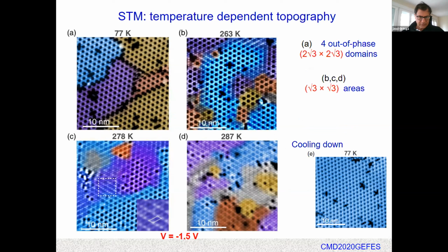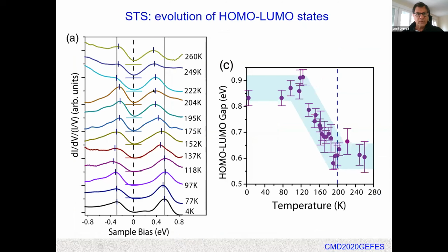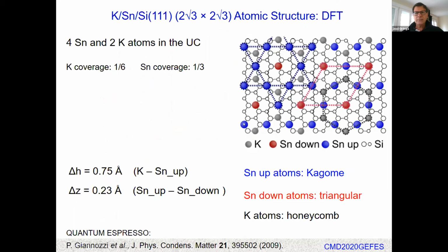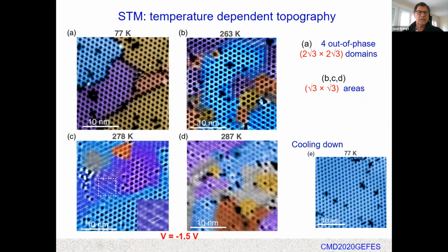STM topography for the voltage of −1.5 V, so occupied states. At 77 Kelvin, at low temperature, we see this structure, which corresponds to the 4 out of phase 2√3×2√3 domains that we have in this surface, indicated by the different colors. So I have to say what these 4 out of phase domains are. I'll go back to the structure. In the 2√3×2√3 unit cell, there are 4 atoms, for example, these 4 atoms. And depending on which one of them is the down atom, we have a different ground state, so we have a different domain. So these are the 4 different domains that we have here, which are out of phase.